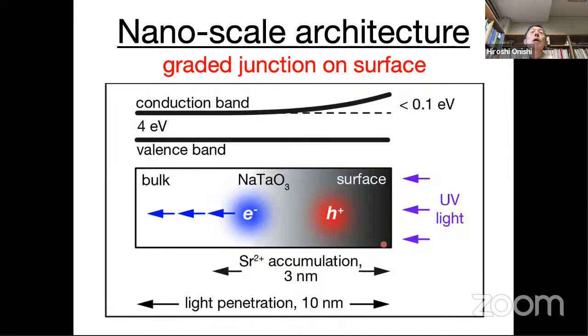So now we come to the final illustration. By putting strontium cations into sodium tantalate, the strontium was enriched at the particle surface, making a 3 nanometer thick strontium accumulation layer. Here, strontium concentration is large, and in the bulk particle, less. And by putting in strontium cations, the conduction band of the sodium tantalate is lifted up by a small amount. Now we irradiate the particle with UV light, and electrons are excited from the valence band to the conduction band.